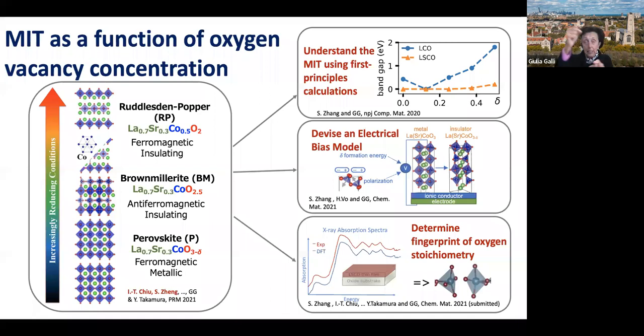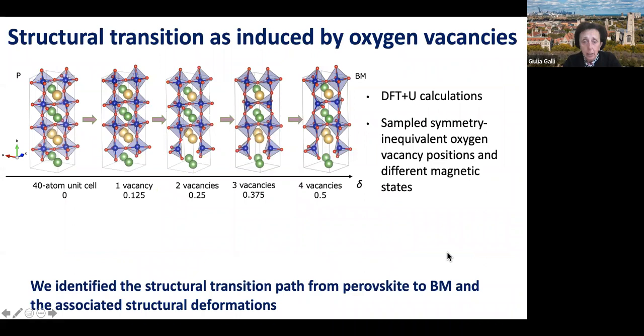And these different structural arrangements are associated with different magnetic and electronic properties that we have studied. And with the three goals: understand the metal insulator transition, devise an electrical bias model to actually trigger the transition, and finally, and we are still working on this difficult problem, determine the fingerprint of the oxygen stoichiometry that is so important, so as to tell experimentally what is the oxygen vacancy content of a specific sample that you want to use to create your device. So now I'm just going to tell you the result of all these three studies without, of course, any details. And the results are here.